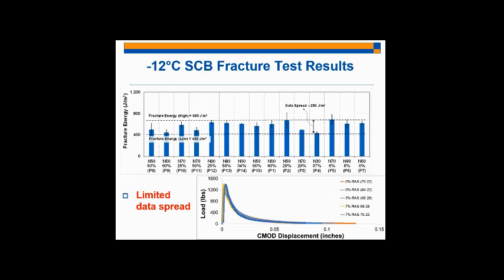And so the bottom right corner of the slide shows the load displacement curves for these low temperature tests. So you can see that for about 5 or so laboratory produced mixes that we've developed, from 0% RAS to 7% RAS with varying PG grade binders, the load displacement curve is basically identical. These mixes are not performing any differently under low temperature conditions. And they're very different mixtures. You're going from 0% RAS to 7% RAS, which is about 30% asphalt binder replacement.